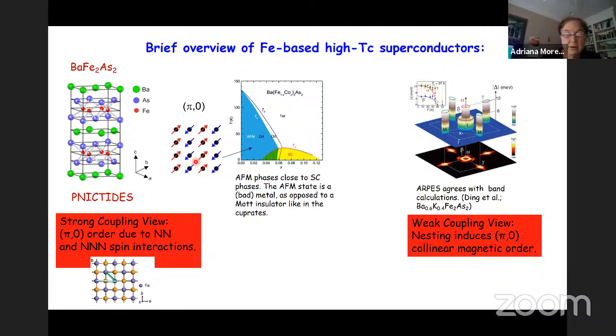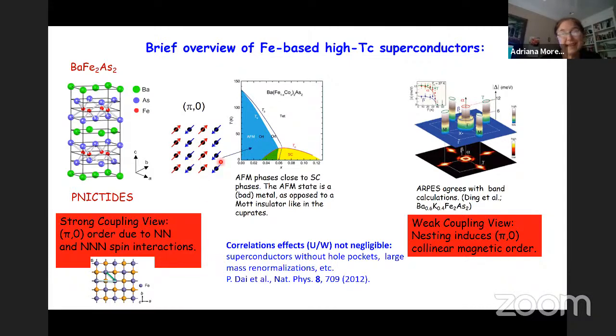However, later on, it was found out that neither of the extremes was a good place to start, and actually the intermediate values of U over W were the most relevant. In particular, against the weak coupling picture was the fact that there are some materials that do not have the hole pockets at the center of the Brillouin zone, so there is no nesting, but still this kind of magnetic order is observed.